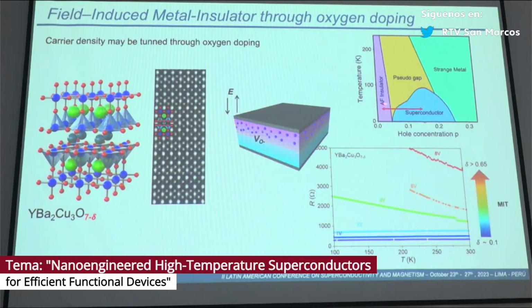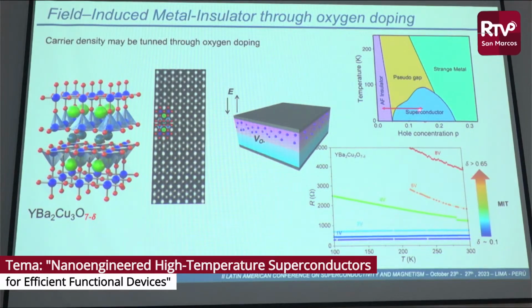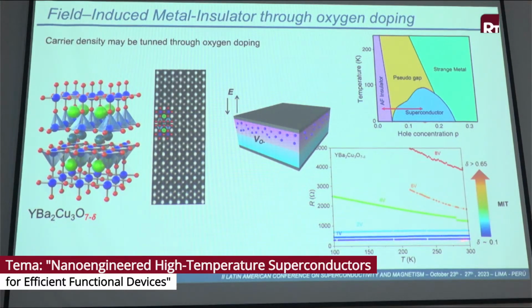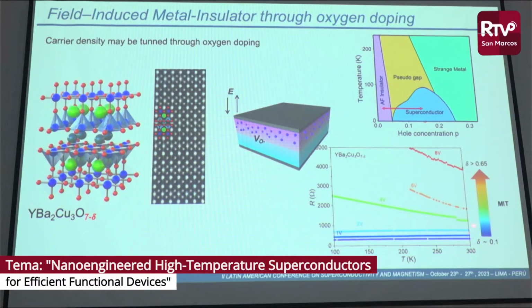So by changing the oxygen in the system, we can go from the insulating to the superconducting state, and we can change completely the electronic properties of the system. In this graph here, I show the resistance versus temperature of a single layer, which has been switched to different states, meaning that we have gone through this axis by applying voltage pulses. For example, we see here that starting from the superconducting state, this one, which has a TC, we change to different insulating states by applying different voltage pulses, which means that we reduce the concentration of the oxygen in the system. And this can be induced in a reversible way. We can go from one level to the other in a reversible way.